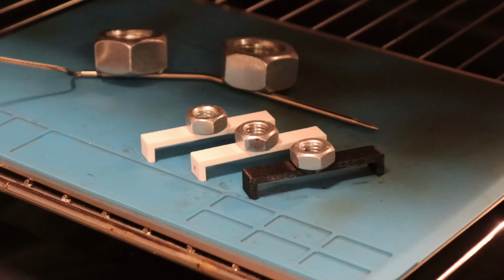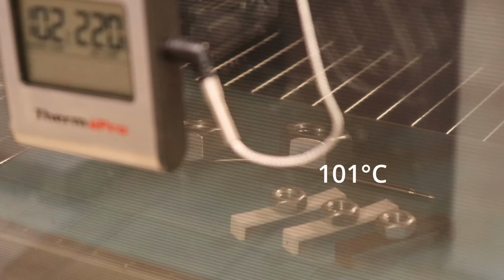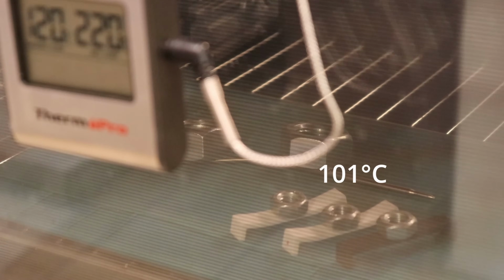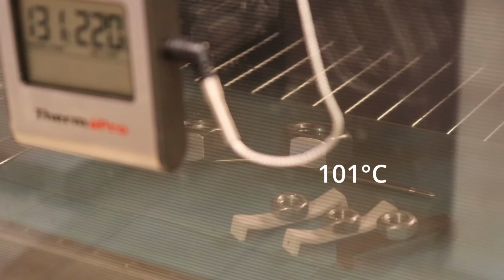Temperature test in the oven. Usually regular ABS or ASA starts to deform at 90 degrees Celsius, but here it was a little bit higher, they start to deform at 101 degrees Celsius. And the third object is the PET-CF by Siraya.